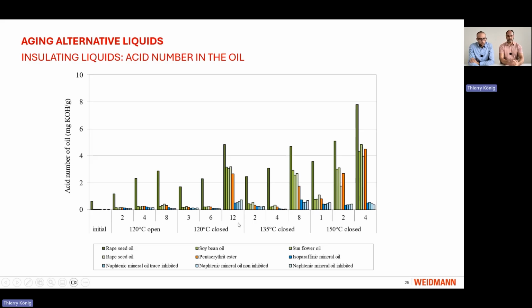In the closed system, we can see an increase nearly at the end of this experiment, in that the acid number is increased in the ester liquids. This can be seen more extremely in the 135 degrees closed system and also in the 150 degrees closed system. And this increase of the acid number is caused by this hydrolysis chemical process.